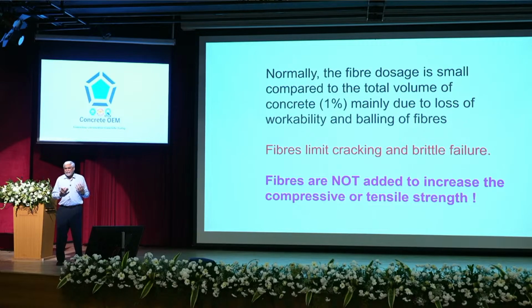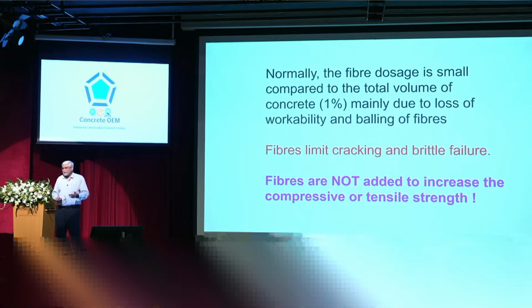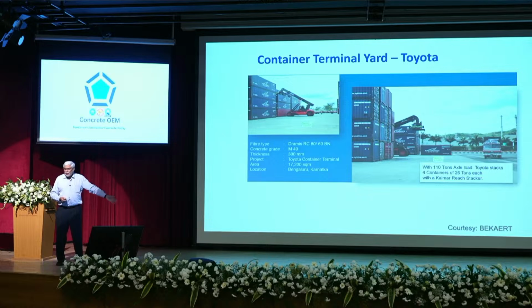Fibers are not added to increase strength. Again, some people say, I put fibers so strength should go up. No. If your strength should go up, decrease water cement ratio. Not add fibers. Fibers are not there at the dosages we use to increase strength. Okay? It's a misconception again that we have to get rid of. Fibers are not meant to increase strength. If I want compressive strength to increase, decrease water cement ratio, use a good super plasticizer, and ask for a higher grade. And there have been a lot of cases.